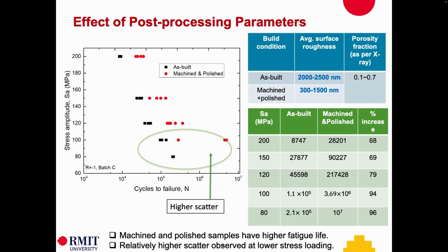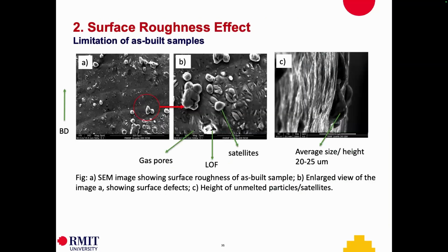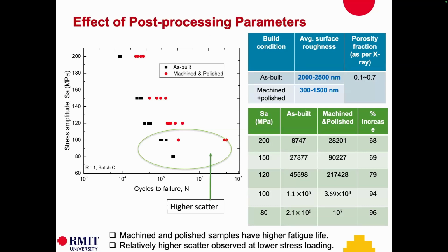So you can see clearly different stress loading, as-built has much lower life, at least 1/3 of the machined and polished cases. And for the lower stress loading, of course, the same thing persists. So we found basically it's clear if you improve surface roughness, reduce surface roughness using machining and polishing, it pays off. You get definitely much higher fatigue life.